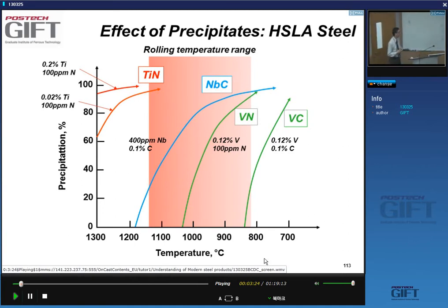And so that is one of the ways people use, in certain steel products, to have very fine, guaranteed very fine precipitates that are formed at low temperatures. But again, so important in this entire discussion is the composition of your steel, yes? What we call the nominal composition. So the percentage of, for instance, niobium, percentage of carbon, the percentage of nitrogen in your steel, and the temperature is important, right? And depending on the composition and the temperature, you may or may not see much of the precipitation.